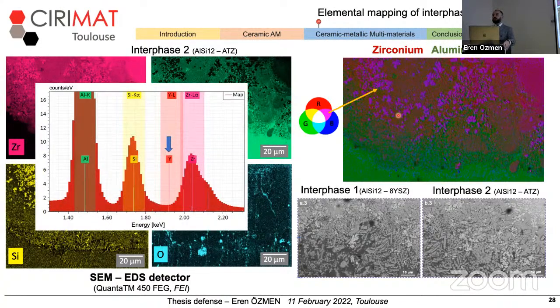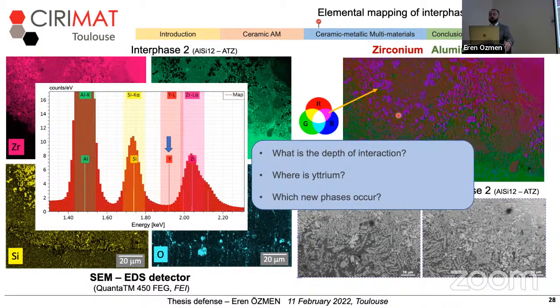Another interesting outcome from this measurement was the inability to detect yttrium in this area. As yttrium is used as a stabilizer in the zirconia structure, it's surprising to not detect yttrium here while zirconium is existing in the interface. So this characterization raised 3 main questions in my mind, which are what's the depth of interaction of these elements, how far they go, where is yttrium, what happens to yttrium, and which new phases occur among these unexpected elements.